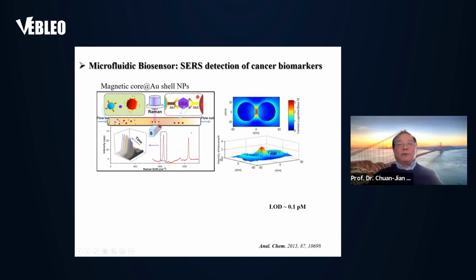All right. So the final example is we use this nanoparticle as a platform to detect cancer biomarkers. Basically, we bioconjugate nanoparticles with magnetic particles and gold nanoparticles to form so-called hotspots. The hotspots allow you to detect by Raman spectroscopy with enhancement. There's all those magnitudes of enhancement. You can also use a magnet to concentrate the nanoparticles, because the superparamagnetic particles are reversibly attracted to the magnet, so you can achieve concentration. And the hotspot, as illustrated by the theoretical simulation, is in between the particles. It has a strong enhancement of the electromagnetic field, lowering the detection limit.